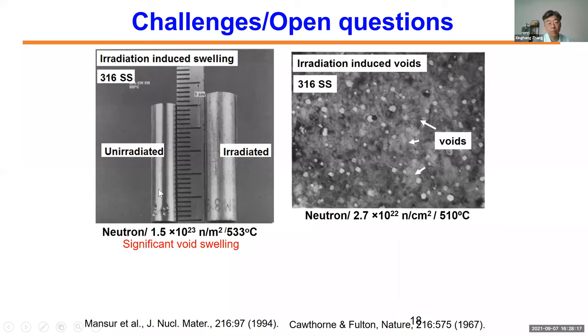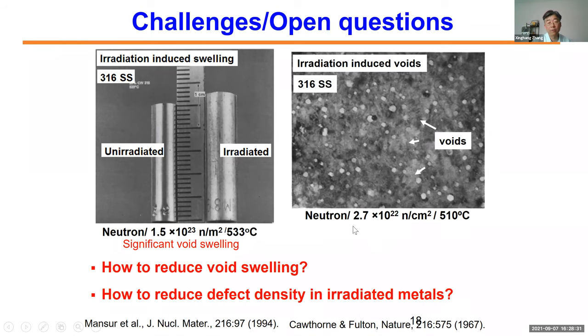So this is a bar before and after radiation. Tremendous volume expansion, mostly because we have introduced a large amount of voids. The atoms went away, and voids were left behind, giving you the so-called classical void swelling phenomenon. Battling against void swelling has been an ongoing challenge for the community. And one of the things we will have to do is to reduce defect density for materials under radiation.